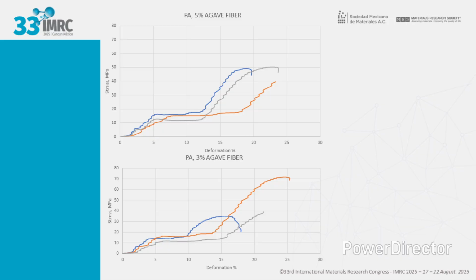Behavior with 3% agave fiber, bottom graph. There is a more marked dispersion. In the orange repetition, a stress of almost 75 MPa was observed with high strain, almost 25%, while the other two, blue and gray, are in the 30 to 40 MPa range and fail prematurely, at 15 to 18% strain.